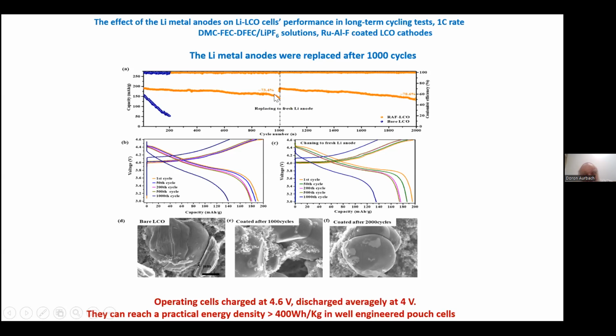So within thousands of cycles, we see it's stable, but after 1,000 cycles, we change just the negative electrode, and we retrieve the stability, and now we could run another 1,000 cycles with our favorite coating and with our favorite electrolyte solution. And again, this means that we can guarantee very high energy density for this type of cells.